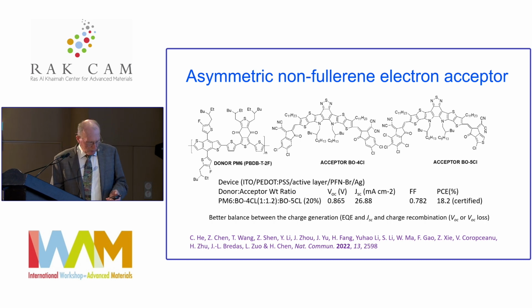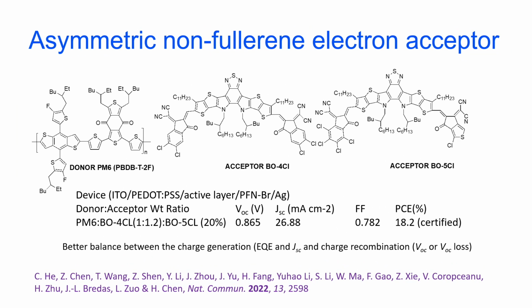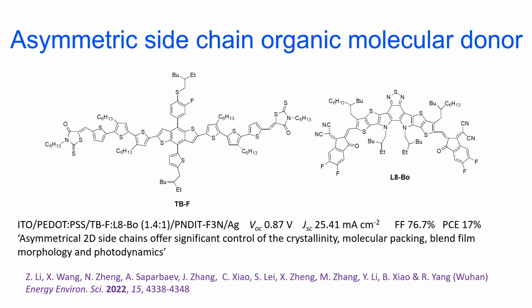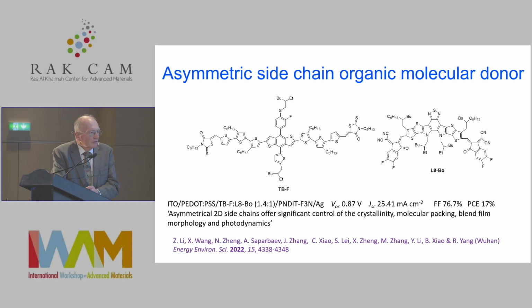So there was some very important computational work. It's important to say that now people are doing computational work. Jean-Luc Bredas's group contributed there to the overall understanding of device performance and efficiency. So you can also play the same game and make the donor molecule unsymmetrical. And you'll see here the asymmetry is the difference in this group versus this group here. And again, a non-fullerene acceptor and a 1.4 to 1 blend of these two materials. And they argue that the asymmetric, we call this the 2D side chains because they're in the two-dimensional asymmetry here they're talking about, offers significant control of crystallinity, molecular packing, blend film morphology, and photodynamics. And again, through a series of studies, this is a group in Wuhan.